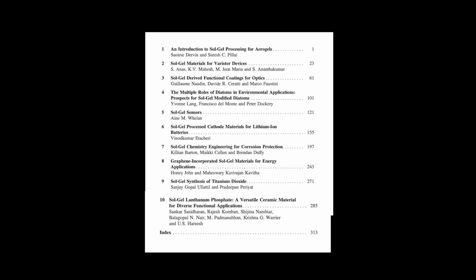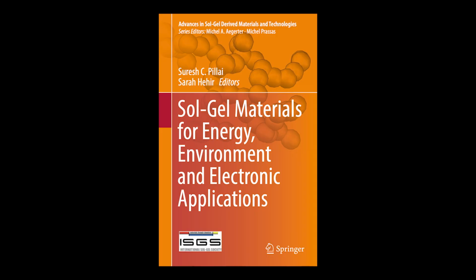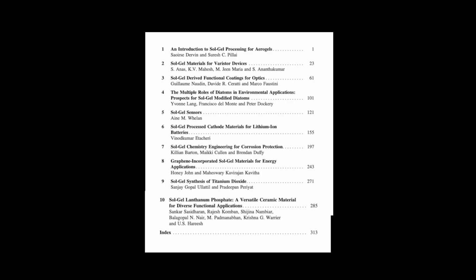And finally, before we leave graphene, we see that performance boost carrying over into Li-ion batteries as well. Yes, definitely. The chapter highlights TiO2 graphene nanocomposites synthesized via sol-gel methods. These materials have achieved charge capacities roughly double that of using pure TiO2 alone as an electrode material. In lithium-ion batteries, TiO2 can act as an insertion material for lithium ions during charging and discharging. Adding graphene enhances this process significantly by providing both high surface area for rapid ion movement between the electrolyte and the electrode, and also excellent electrical conductivity within the electrode itself. This facilitates much faster charge and discharge rates and improves overall capacity.